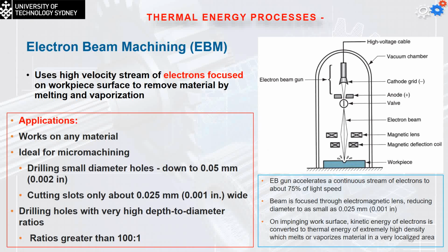The applications are works on any material. It doesn't matter if it's conducting or non-conducting. It's ideal for micro machining processes. It can drill small diameter holes down to 0.05 millimeter diameter, cut slots only about 0.025 millimeter wide, and drill holes with a very high depth to diameter ratio, greater than 100 to 1. That means the length is 100 times longer than the diameter.